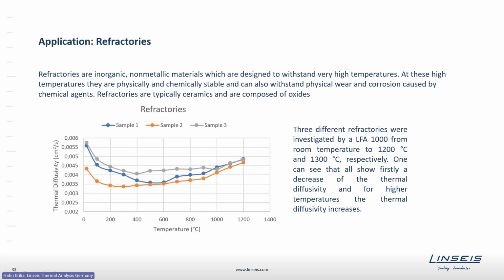We also performed some measurements on refractories, so typically ceramic-based materials, which are very stable at high temperatures. Here a test was performed on 3 materials up to 1200 degrees Celsius, and we can see a good difference between those materials. And this test is useful for simulations, for example, for thermal management.